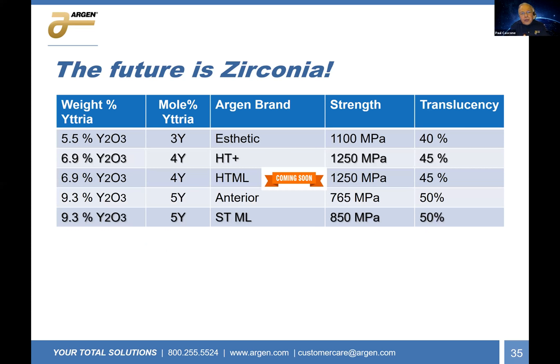Now, there's a variety of different zirconias on the market. The first ones that came out, as I mentioned, were 3Y. That's, in our case, aesthetic. But it has a strength of 1,100 megapascals and a translucency of 40%. The next one that came out was a 5Y material. That had a much better translucency, but the strength was substantially lower. So we were looking for a material that would have a higher translucency, something between 40 and 50, but yet not lose the strength. And we were able to develop a product that we call HT+, and this is a 4Y material, where the strength is actually higher than the 3Y material, but the translucency is also higher.